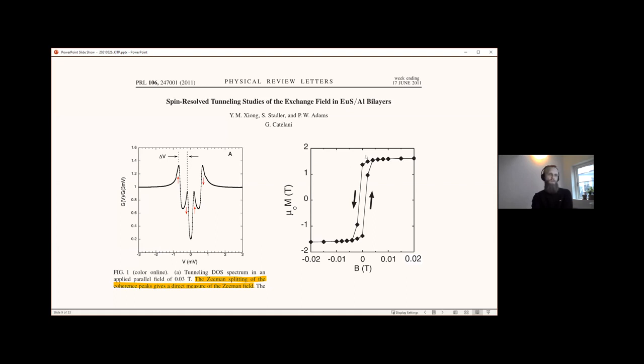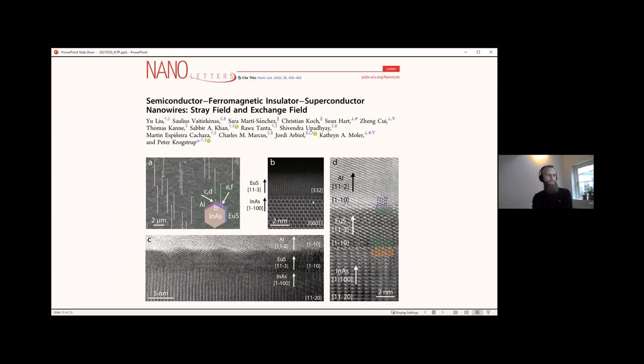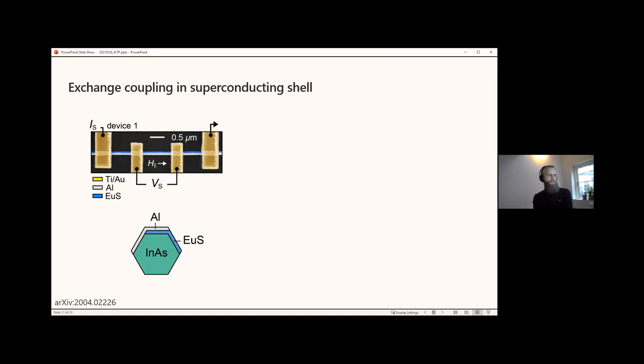And this motivated us to develop a new system similar to the aluminum indium arsenide epitaxial wires. But in this case, we also include a europium sulfide film in between the two materials. In this work, led by Yu Liu and Peter Krogstrup's group, they showed that the system is epitaxial in all cases in between indium arsenide, europium sulfide, and aluminum, and these wires look quite nice from the material perspective. So we continued with them and started by investigating the properties only of the superconducting shell.